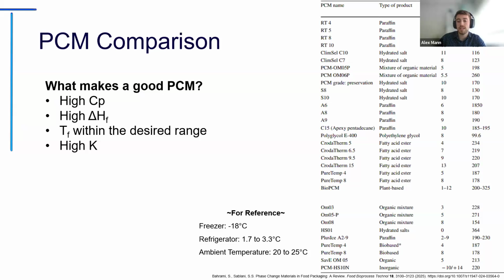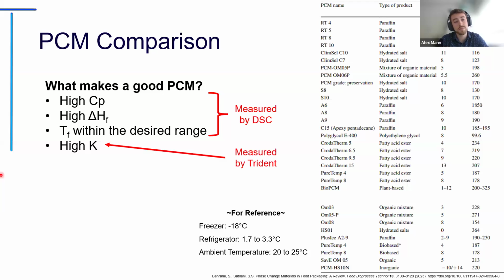Next, it needs to be melting in the desired range. So you could have the world's best PCM, but if the phase change is at 200 degrees Celsius, it's not going to be useful for food storage. And as Arya mentioned, you're going to need to know the thermal conductivity, because we want a high conductivity so that the PCM will absorb more heat from the food and there will be temperature equilibrium. And the first three are easily measured by DSC. We can get specific heat capacity, we can get the temperature of fusion, as well as the energy associated with it. And as previously mentioned, the K can be measured by Trident.